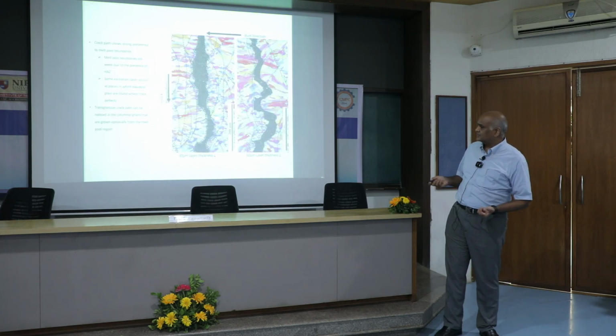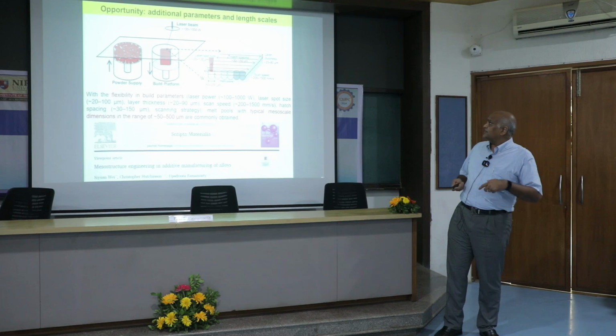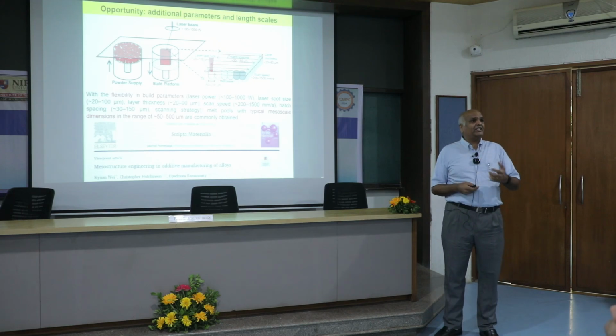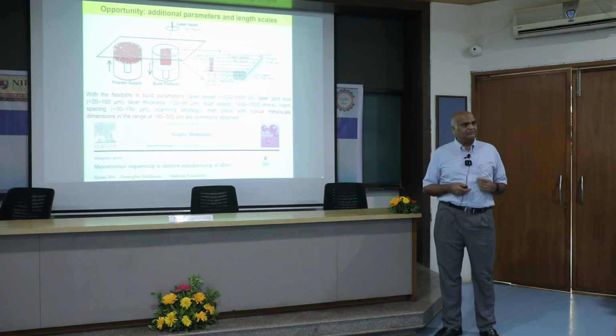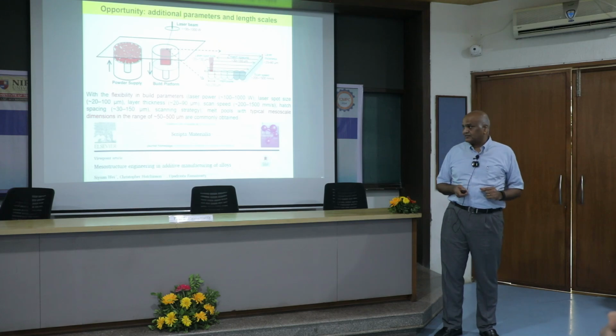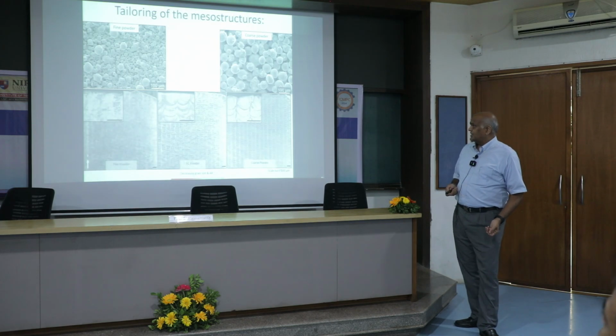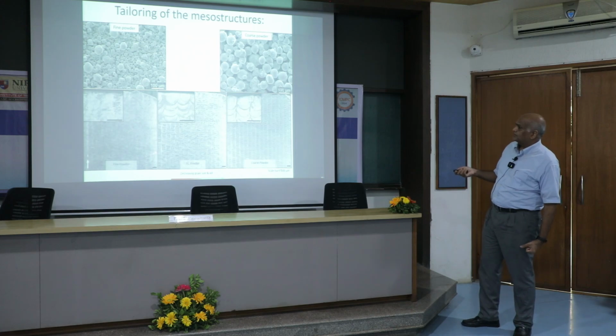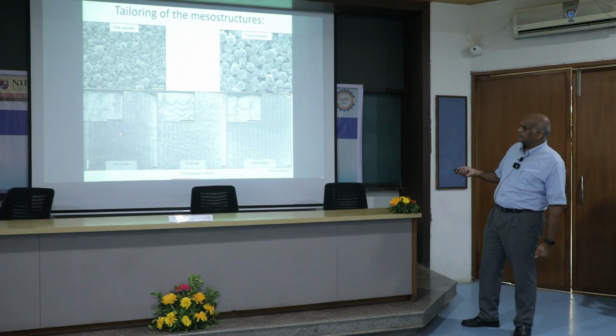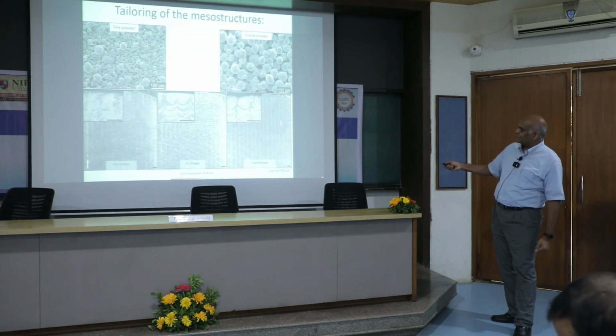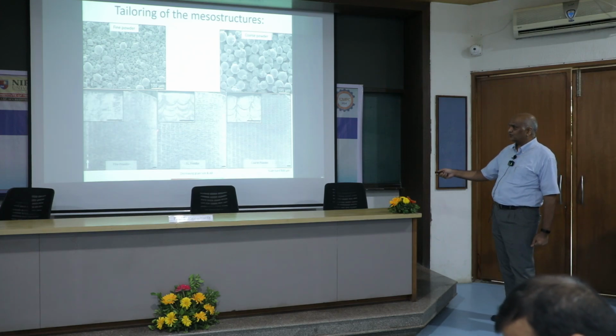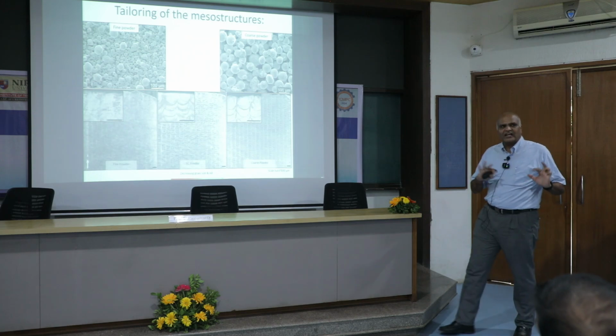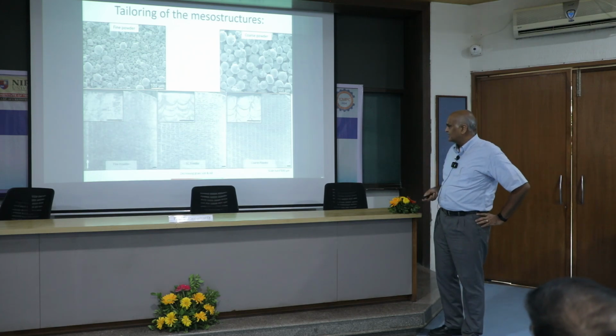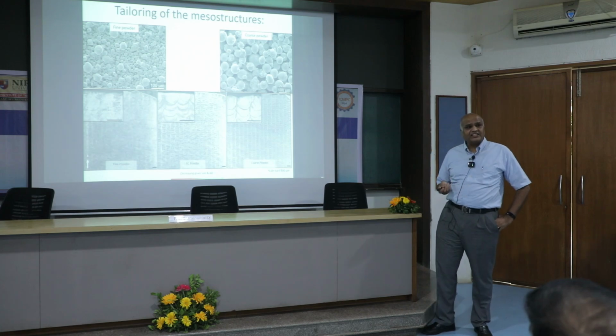You can see the crack deflections in aluminum, silicon, magnesium, and so you can actually play around with this as an opportunity to change the length scales in the material. For example, here you see that in the DED, if you use fine powder, you don't get it, but if you use coarse powder, you can get a very distinct mesostructure, and if you use in between, you get something in between. So we have a lot of options. You can change the mesostructure as you wish in these materials.